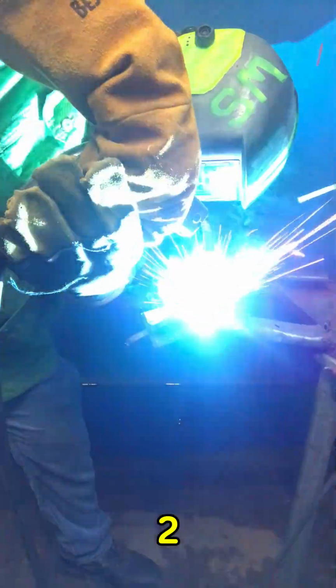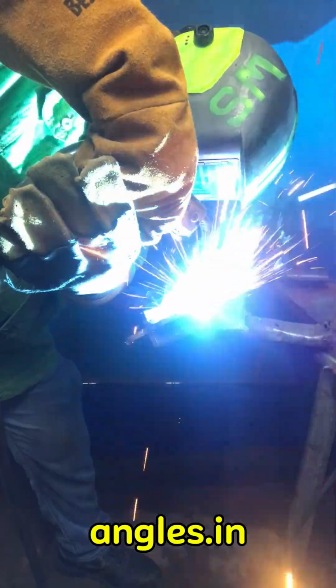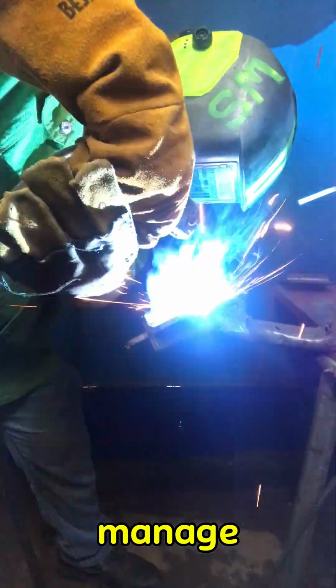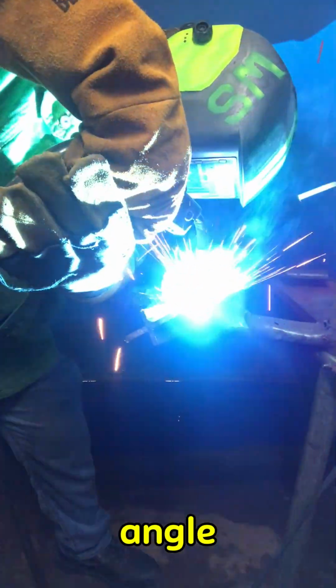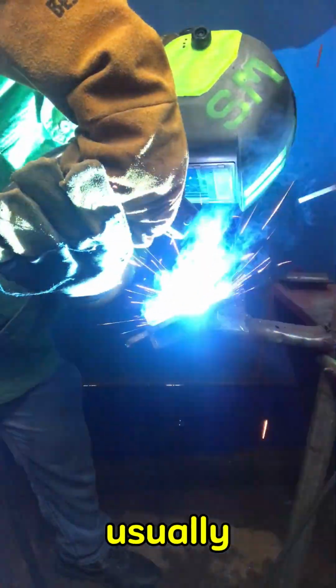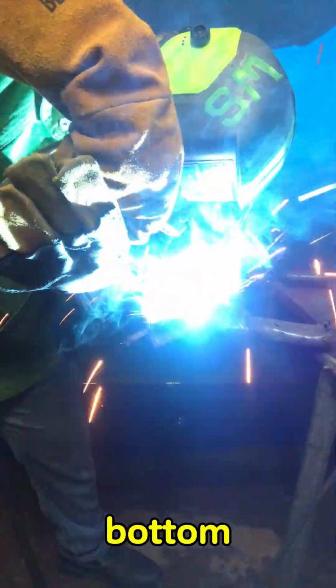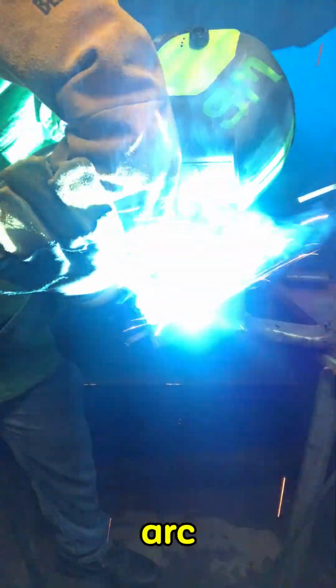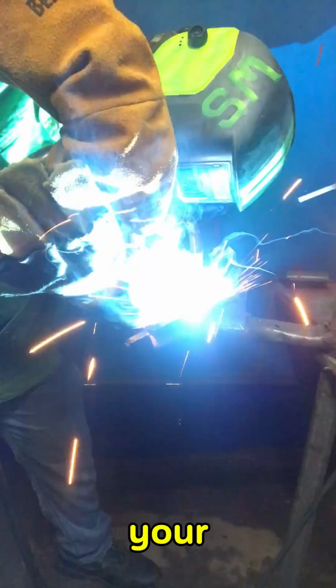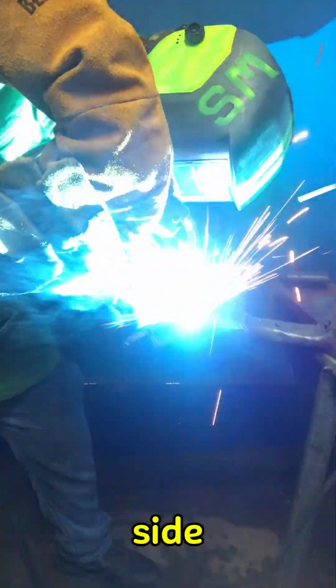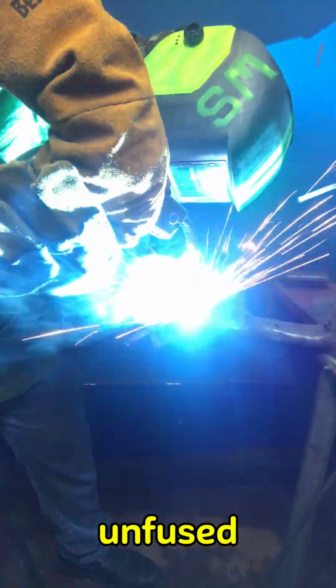Mistake number 2. Bad torch or electrode angles. In 1F, you have 2 angles to manage, work angle and travel angle. A common error is favoring one plate, usually pointing the torch too far down toward the bottom plate. Heat follows your arc. If you point at the bottom plate, your filler metal builds up on one side, leaving the top plate completely unfused.